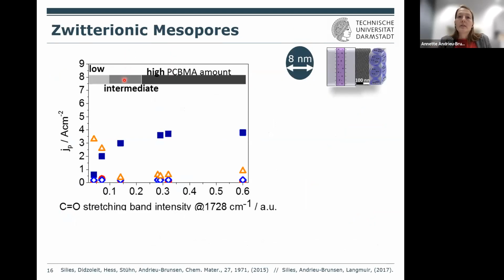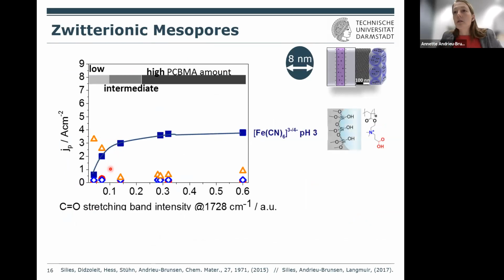If you then switch the polymer again, in this case, to this candidate, which can be zwitterionically or positively charged. So here you have a positive charge, and this is basically the same case as we had with polymetac before. And what you see here, independent of the polymer amount, is again this gradual behavior for the pore accessibility of a counter ion. And for the positively charged molecule, this is basically quality control. If your pore system is intact, the transport is almost zero.